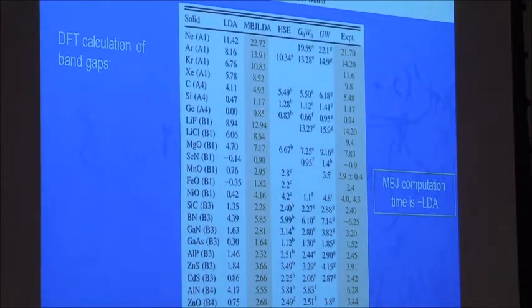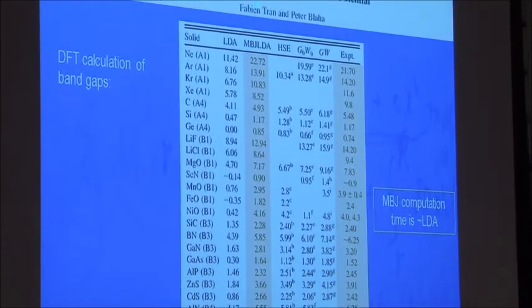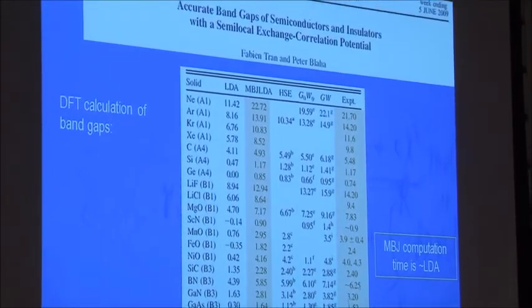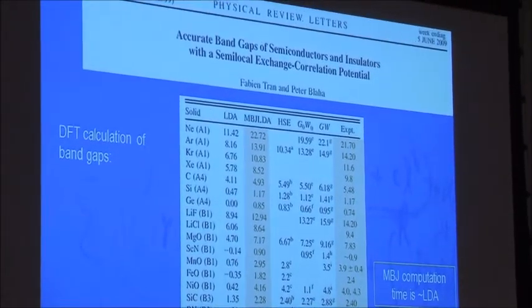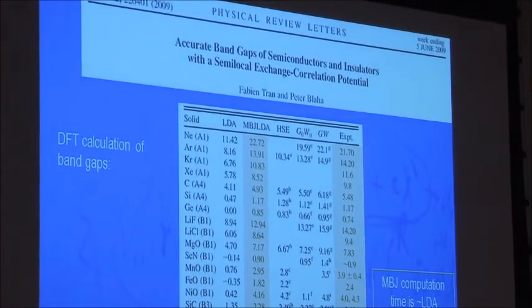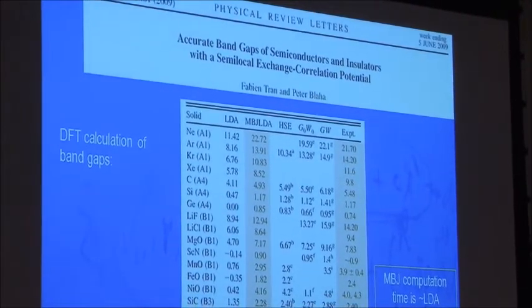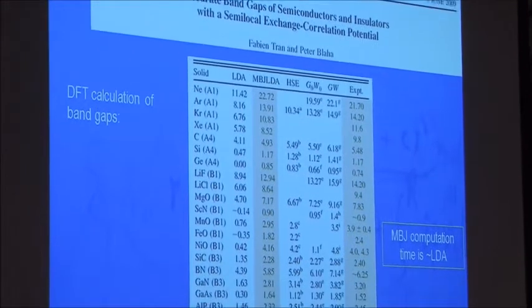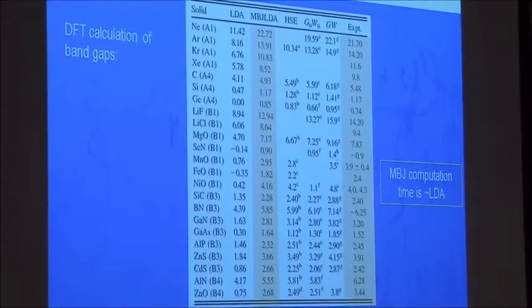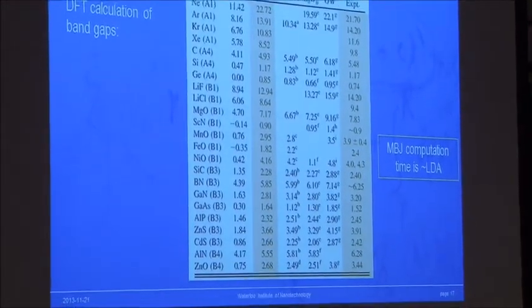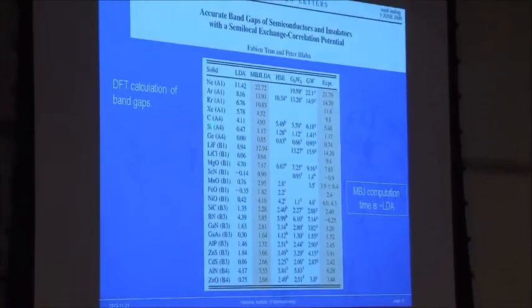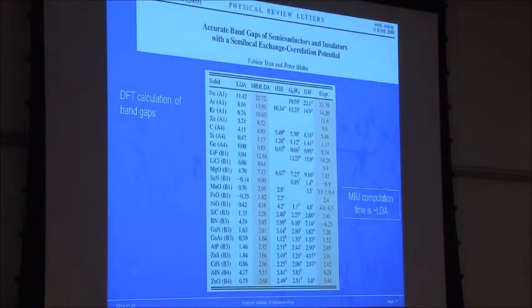The reason is that they use something called semi-local exchange. Local exchange is wrong. Completely non-local exchange is good, but can only do small systems. So they made something in the middle, and it sort of works. Essentially they solved some issues about the discontinuity of your exchange correlation energy and so on, and made sure that this works. So when I saw this paper, I said, that's the savior for our research, and we implemented this method right away.